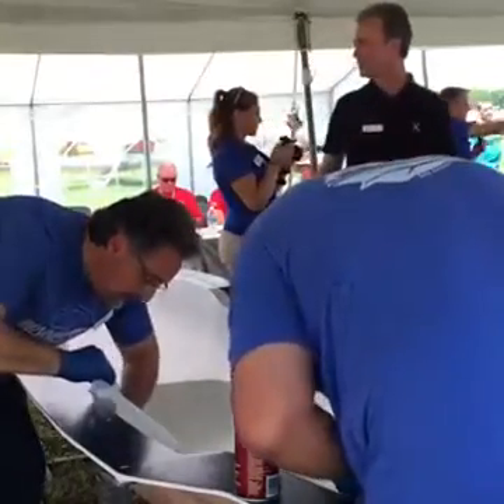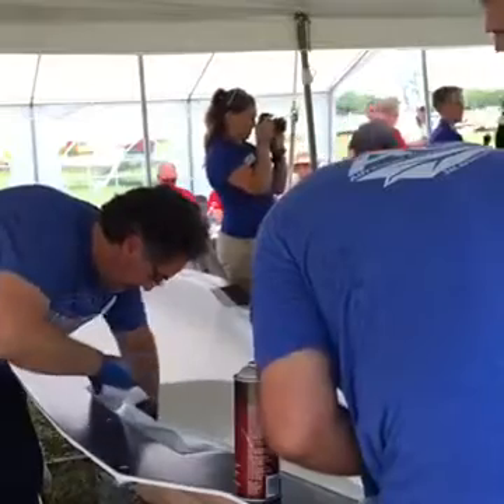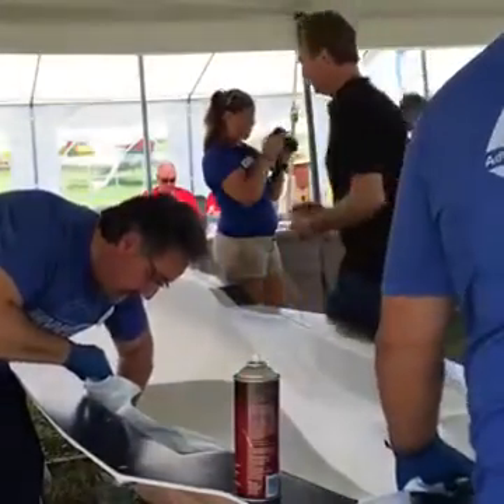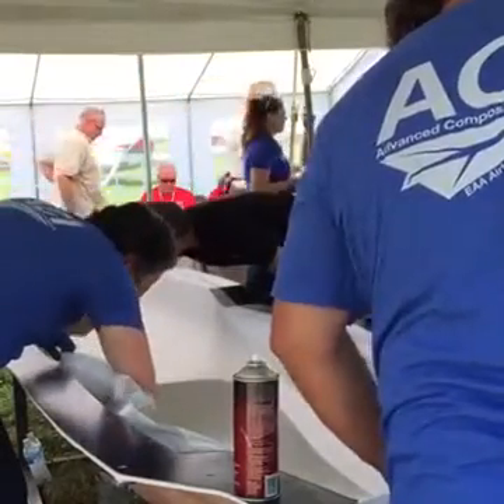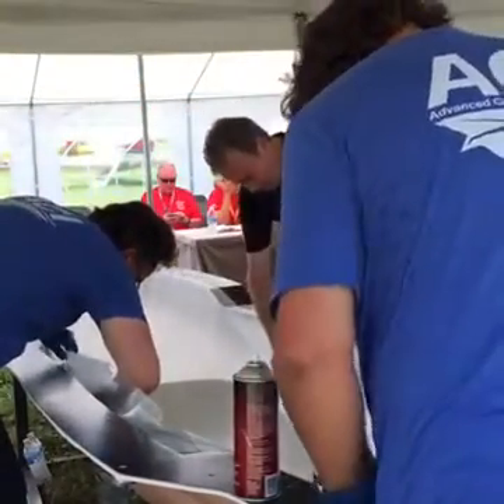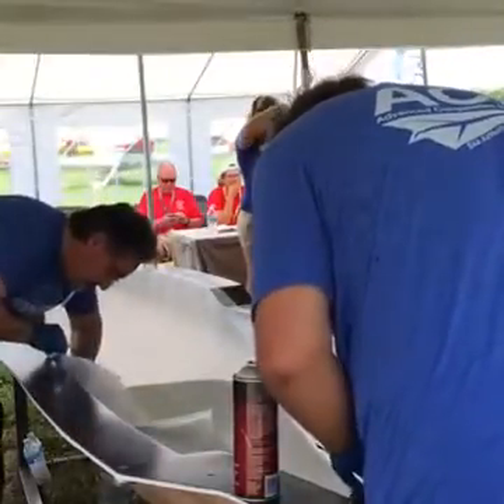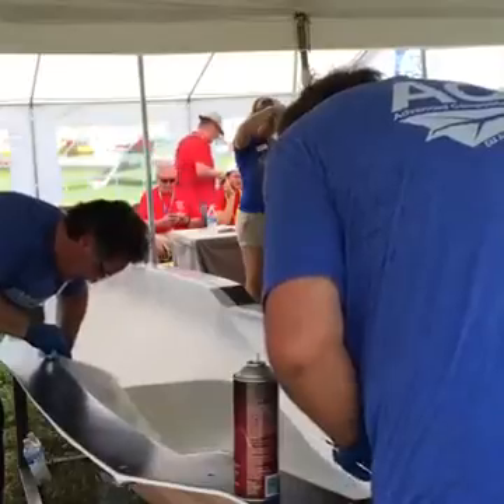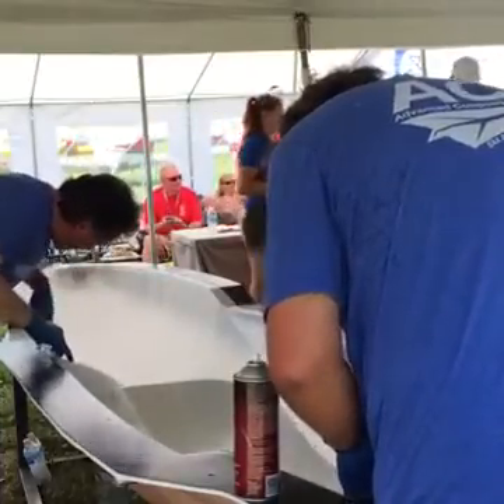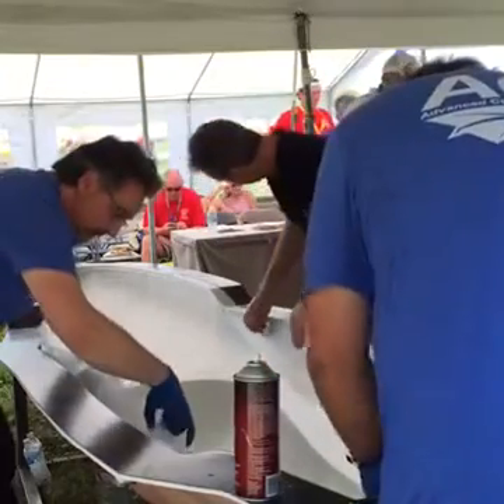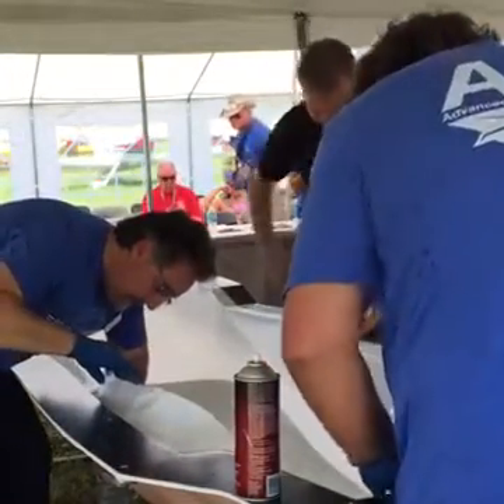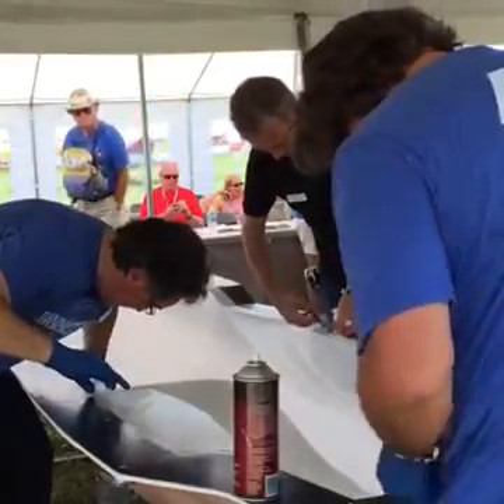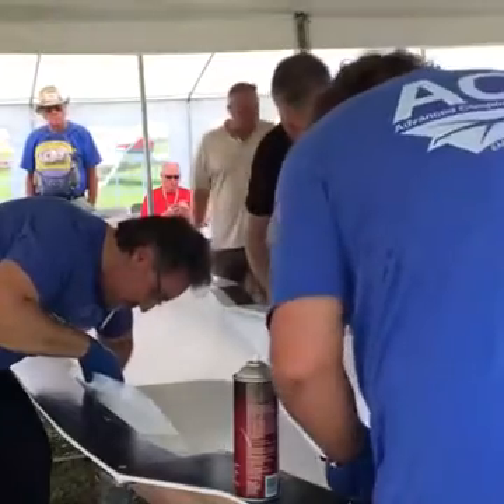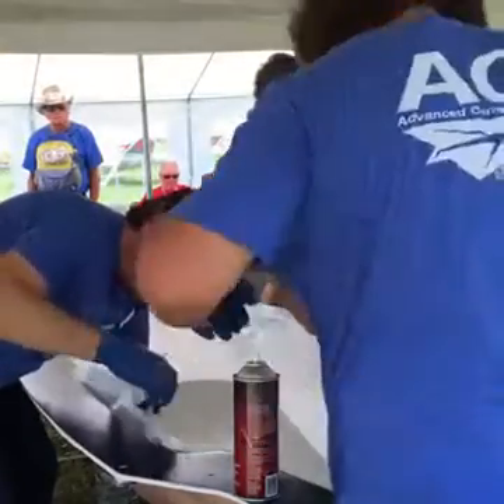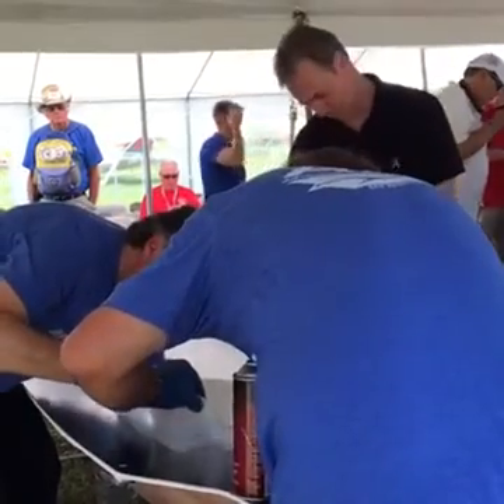This kind of stuff, disturbing the fibers, has no effect. As I mentioned earlier, I'm using the glass as an encapsulator, if you will, for the Enkalon, just to ensure that I've got plenty of resin around the Enkalon fiber. Secondarily, this is a sacrificial block. Because we wanted to show you the finished part and the fibers when the part came out of the mold, we chose not to put it in the mold. So we're going to have to abrade this part and then prime it. This surface here will be abraded to accept the primer, not the structural components that we actually put down.